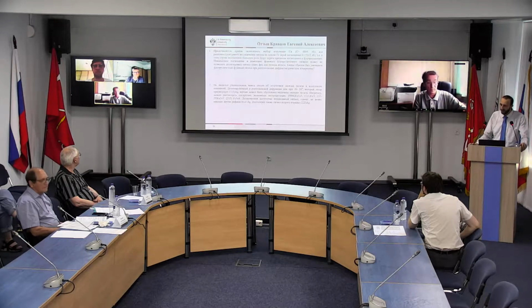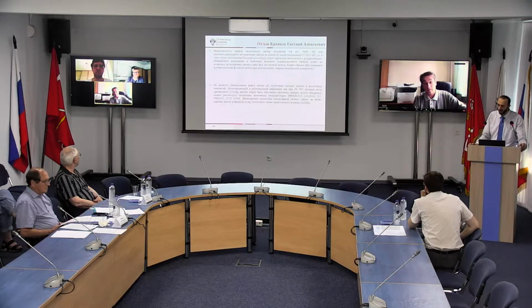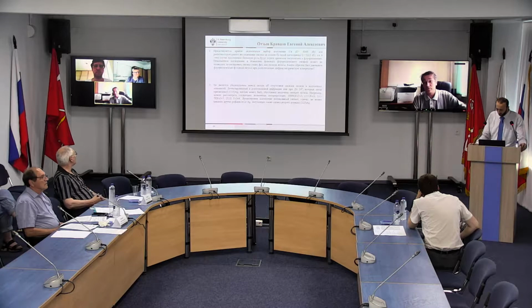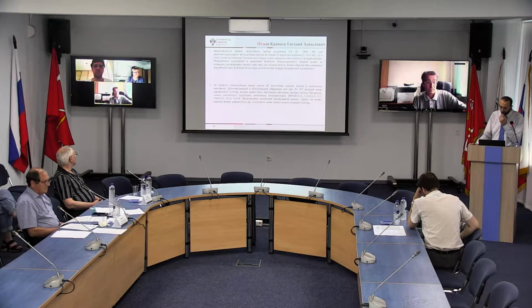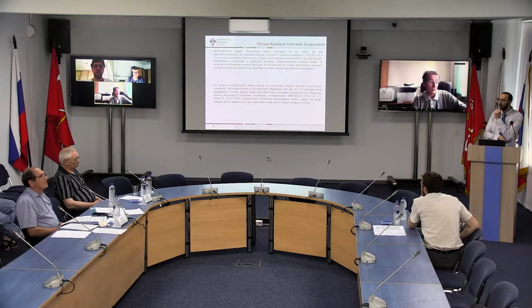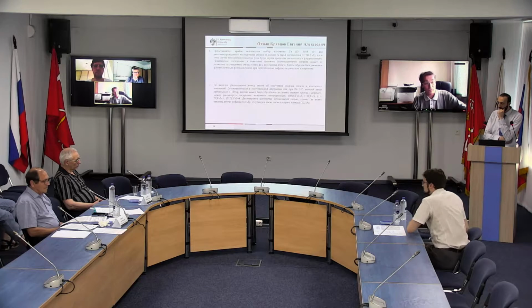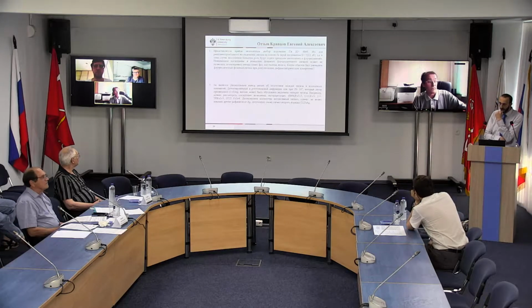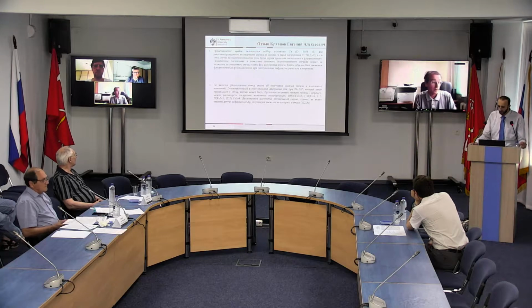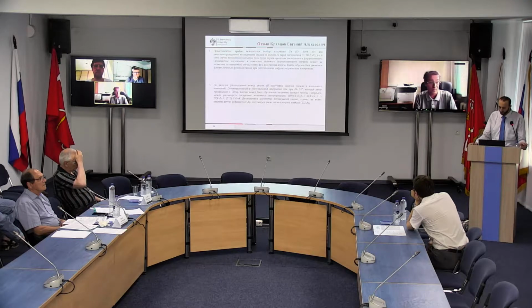I've already uploaded them on the website. I'd just like to shortly formulate them. Regarding the X-ray part of this work, the first point is as follows. In the work, you study nanowires based on iron, and in order to work with iron, the choice of copper radiation, well, it's hard to imagine something worse, because the absorption edge of iron is 7,112 electron volts, and it's quite close to the energy of copper radiation, 8,048 electron volts. So there will be absorption and fluorescence. And if you want to see not just iron but also oxide phases, with such a fluorescent signal you need to fight with it somehow.